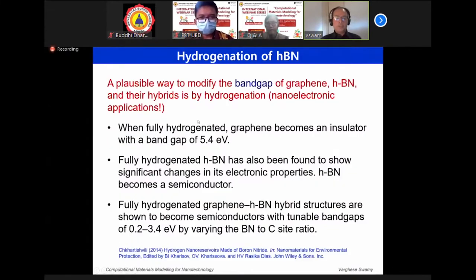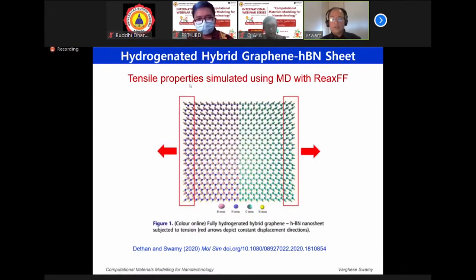Now, another possible way to play with the band gap of HBN and graphene is to hydrogenate it experimentally. That means you can attach hydrogen species onto carbon, boron, and nitrogen atoms. And that way you are able to modify the band gap, which means from an insulator HBN, you can make it all the way to a semi-metallic graphene by just playing with the hydrogen atoms. It's by attaching different atoms and in different proportions. So that was the motivation.